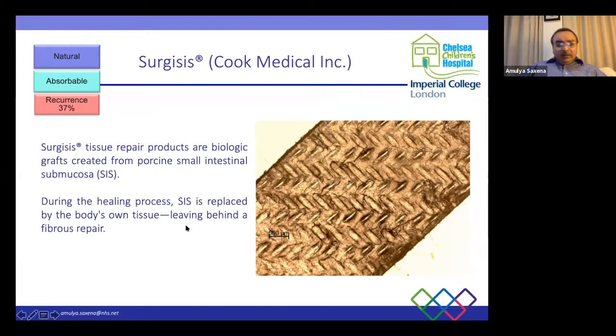Now, we have the biggest problem with Surgisis. Nobody has really reported if they're using four-layered or eight-layered Surgisis. They come in these two variants. Now, it's easy to suture the four-layered variant because it's much easier on the sutures, and when you try to stitch it on the wall, eight-layered are quite thick. They're almost like suturing leather. It's quite difficult to do. So the recurrence cannot be really calculated because there's inconsistency in reporting of whether four- or eight-layered Surgisis has been used.